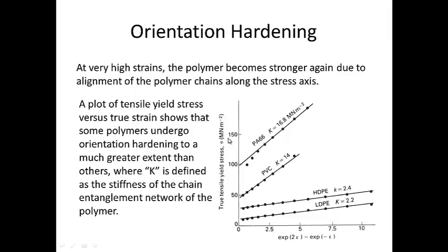If I plot tensile stress along the y-axis versus the true strain along the x-axis, we tend to see a straight line relationship between those two parameters. We also see that not all polymers behave the same way. High-density and low-density polyethylene have relatively low amounts of strain hardening or orientation hardening as the chains line up. But PVC and polyamide 6-6, or nylon 6-6, orient and therefore strengthen much more than polyethylene. The reasoning for this is the nature of the mer units — in PVC, for example, we have chlorine atoms sticking off the side of the mer unit that form stronger van der Waals bonds as the chains become more aligned.